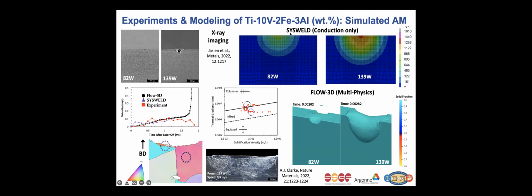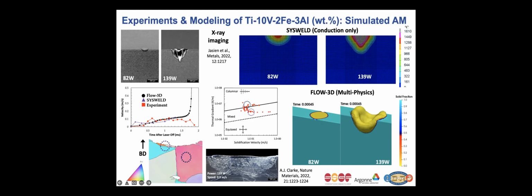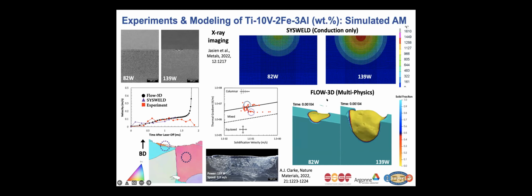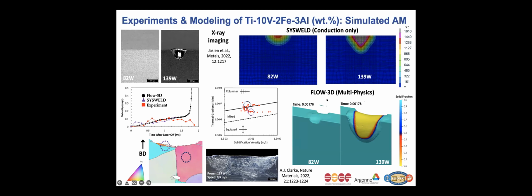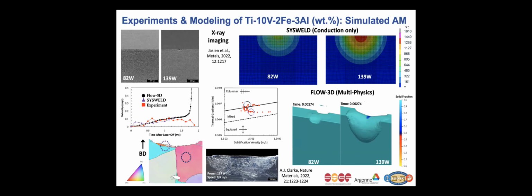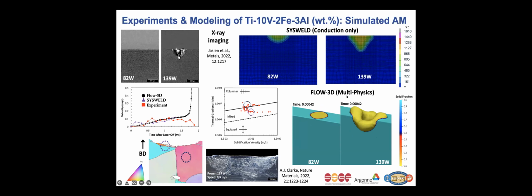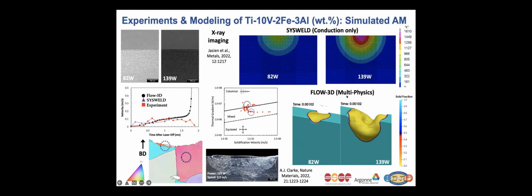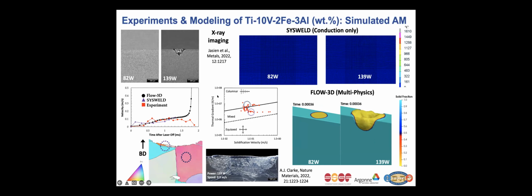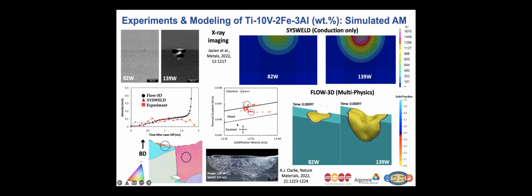Here we have SYSWELD, which is more simplistic and is a conduction-only model, as compared to Flow-3D, which is multi-physics, which is conduction plus convection. Again, this becomes really important as we go to high power conditions where more keyholing is experienced. We actually have to go to a multi-physics kind of model. We can then use this information to inform these columnar to equiaxed kinds of predictions and rationalize the microstructures that we see.